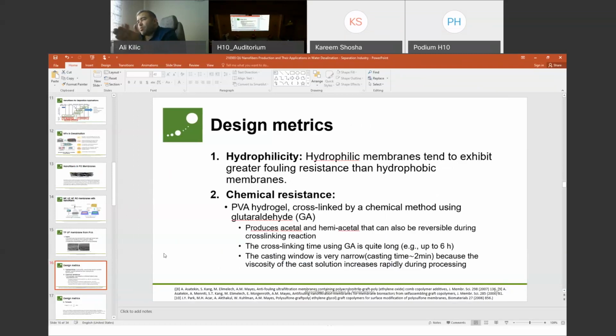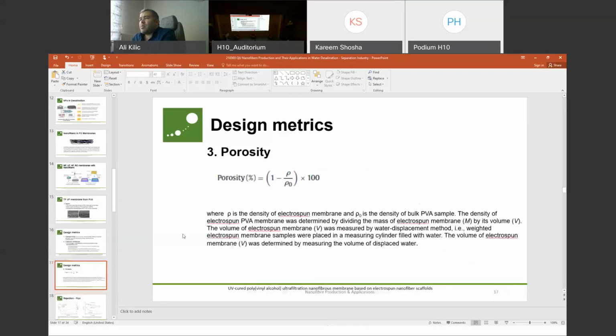For some specific applications like membrane distillation, we may need super hydrophobicity or hydrophobic surfaces. This is also possible with nanofibers since it mostly depends on the chemistry of the selected polymer. But we can easily arrange the hydrophilicity and the chemical resistance. For instance, even for PVA, which is water soluble, if you go for some cross-linking, even the PVA nanofibers stand the required chemical resistance. And other parameters, as I said, porosity, this is basically where nanofibers are doing best for membrane production.